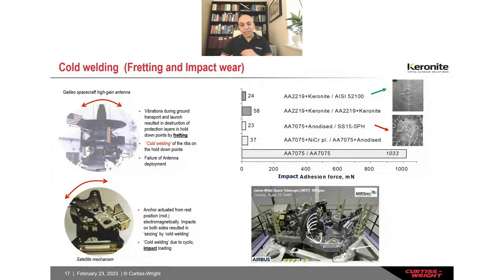On the bottom one is a satellite mechanism, an anchor. It has got a repetitive motion and repetitive cyclic contact impact loading when this part moves electromagnetically from left to right. And what happens is the protective layers at those contact joints are damaged because the coating wasn't good enough or strong enough, and eventually it welds, leading to failure. It doesn't separate. So that's another problem.